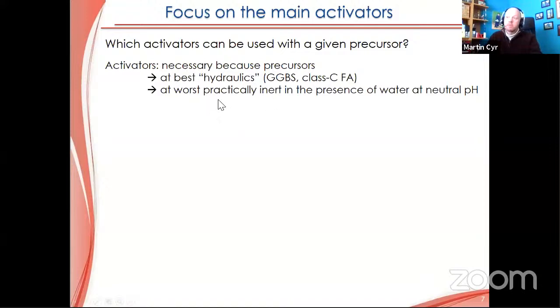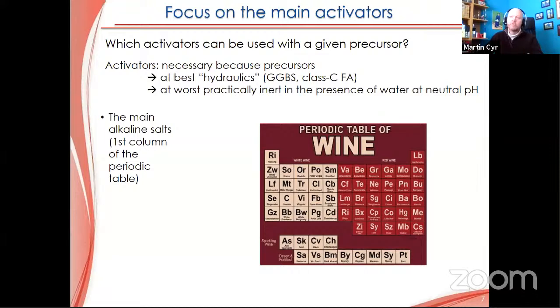And at worst, it is practically inert in the presence of water when we use neutral pH. You put metakaolin inside water, you can wait a lot of time before having a set of the material itself. So we need something to boost the reactivity of the material a little bit. And usually we are using alkaline salts, the first column of the periodic table. Not this one, of course, we are in France, so I found a very nice periodic table of wine, but that's not the one we are usually using.